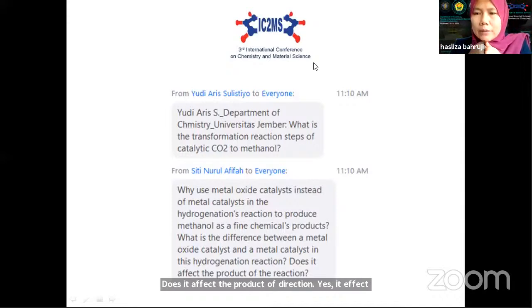The reason it affects the product of the reaction is that the surface basicity might be different depending on the type of metal oxide that you use. The orientation of CO2 when it adsorbs on metal oxide will be different depending on the basicity of the metal oxide support. And also the selectivity is different.